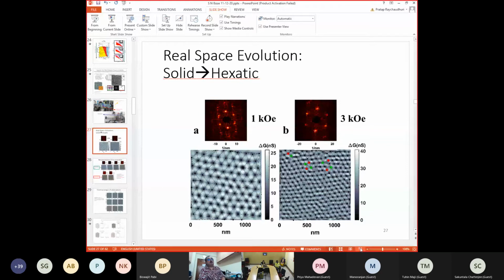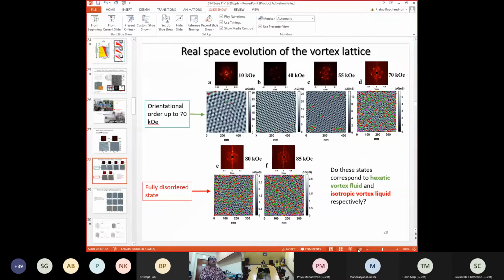We get 1 kilo Ørsted, we have a vortex solid. Then 3 kilo Ørsted, we start having dislocations. And then we have more dislocations up to 70 kilo Ørsted. But we still have the orientational order. Above 70 kilo Ørsted, we have disclinations, and this is the isotropic state. So here all order is lost.